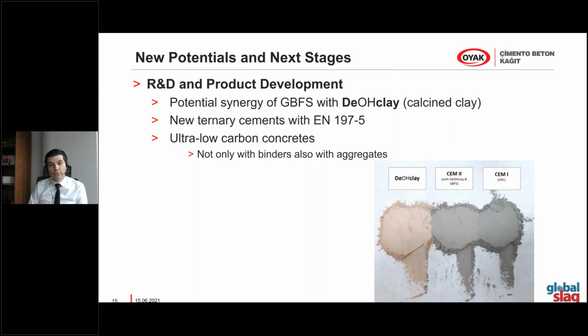New ternary cements: we know that the EN 197-5 standard is ready, and we could mix much more slag and calcined clay in it. We focused on that license, and we will serve our clients with that by the help of the new standard, with higher flexibility and new products. And also ultra low carbon concretes, not only with binders, also with aggregates.